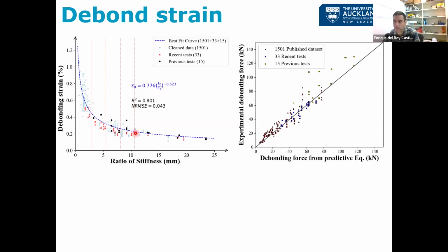With the rupture strain being 1% or 1.2 or 1.3%, that means the efficiency is about 20%. So we need to be very careful with this. We cannot use the rupture strain of the FRP for design.